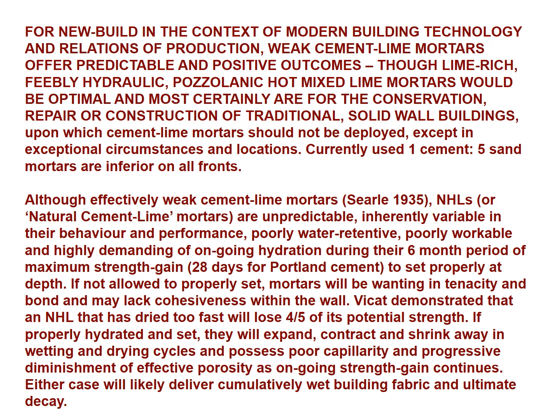Currently used 1 cement to 5 sand mortars are inferior on all fronts, and this was amply demonstrated by the US Bureau of Standards way back in the 1920s and 30s. Although effectively weak cement lime mortars, as termed by Searle in 1935, NHLs, or perhaps better described, natural cement lime mortars, are unpredictable, inherently variable in their behavior and performance, poorly water retentive, poorly workable, and highly demanding of ongoing hydration during their 6-month period of maximum strength gain to set properly at depth.